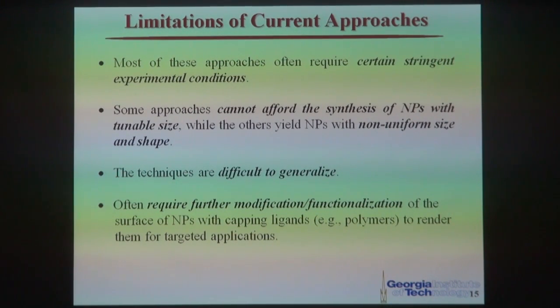However, the other techniques allow you to make particles, but the size and the shape of the particles cannot be well controlled. So more or less, these techniques are very difficult to generalize. One technique only allows you to make one or a few particles of different kinds. And lastly, all these techniques require further surface modification and functionalization of the particle surface with capping ligands, for example, polymers, in order to dissolve these particles in solvent, like non-polar solvent or in water for targeted applications.